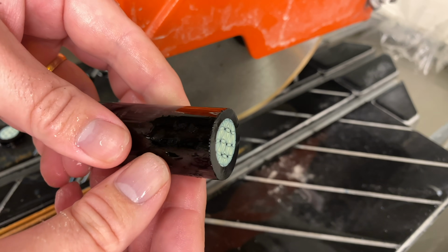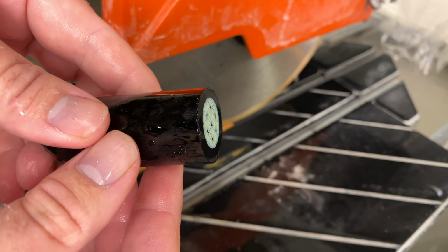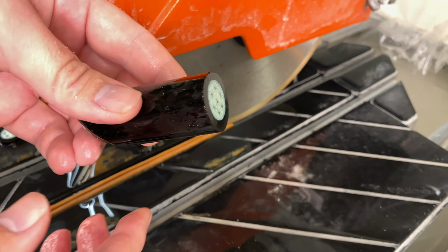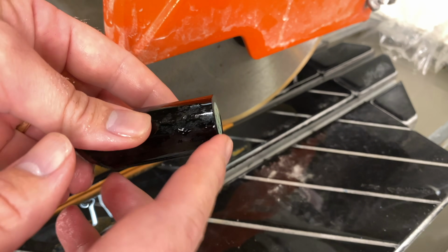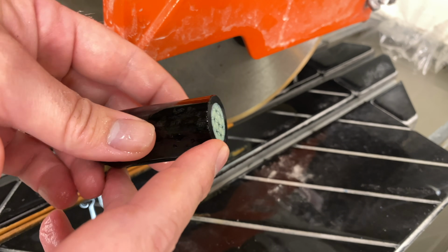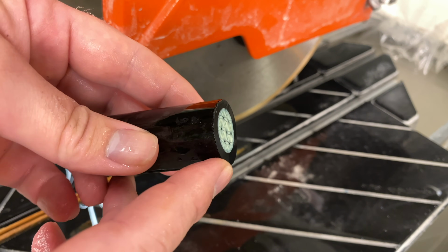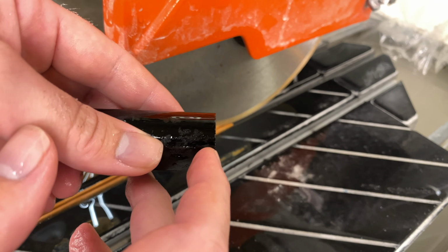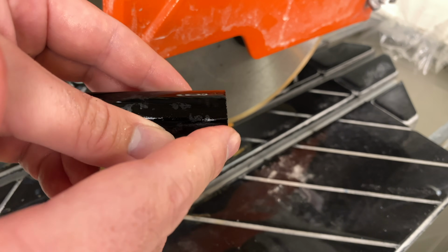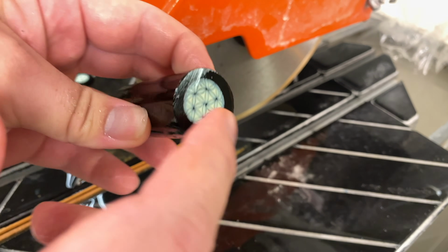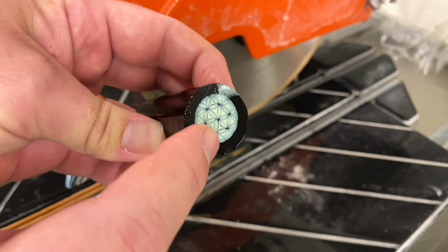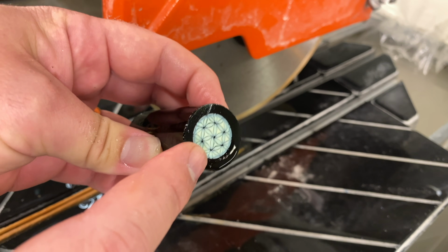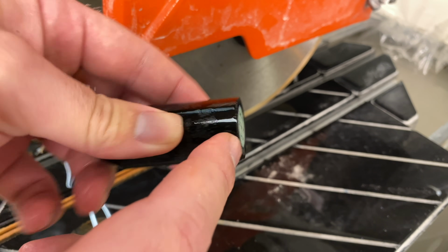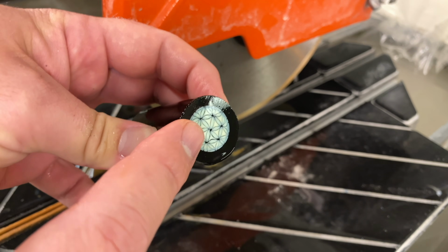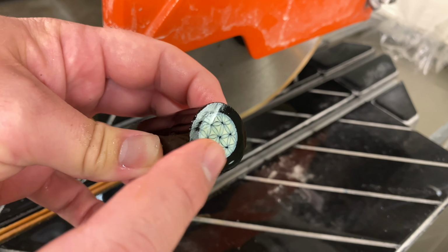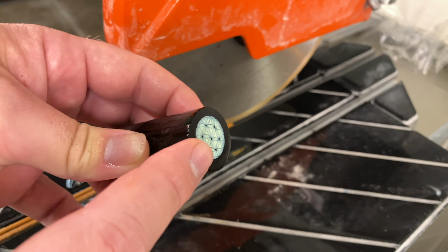So you're really looking at where your priorities lie in terms of blades. Are you looking for the smallest amount of material loss that you possibly can get away with? You may want to look at one of those electroplated thin kerf blades because you're going to lose very little glass from the cut and you're still going to get a virtually chip-free cut. Are you looking for the best surface that you possibly can get? Then you're probably looking for the resin blade, where you're going to get very little, if any, edge chipping, and you're going to get a really nice surface on your millie from the cut that's easy to clean up. You could probably even go straight to a fire polish from a resin blade.